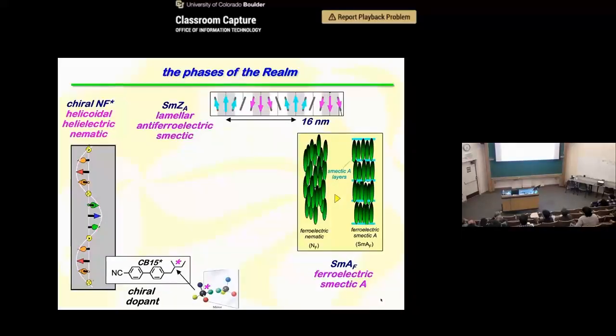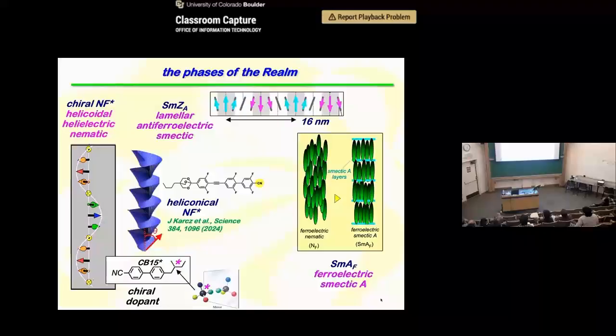Okay, so then there are molecules where these molecules all tilt up. And so a heliconical ferroelectric nematic, where the molecules are basically rotating on a cone. And this can be induced by adding chiral dopant, or there are phases where this happens spontaneously. So you go from a uniform ferroelectric nematic phase transition to a structure like this, which can be either left-handed or right-handed. So then macroscopically you get a phase separation. You have domains where you have left-handed heliconical and right-handed heliconical.